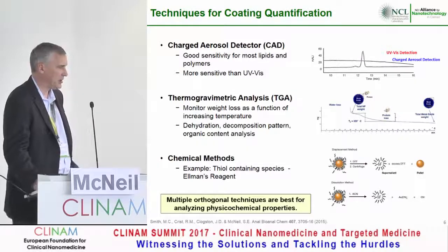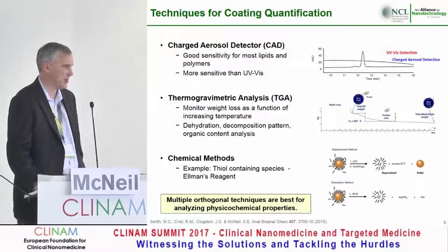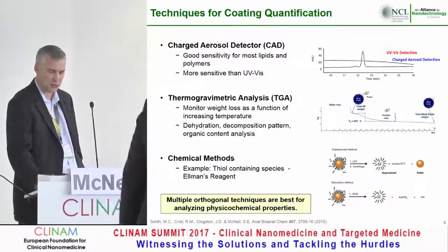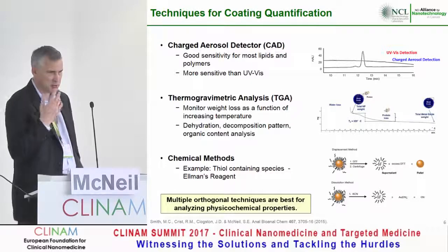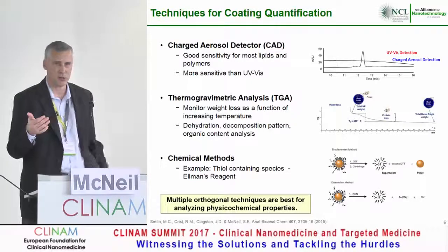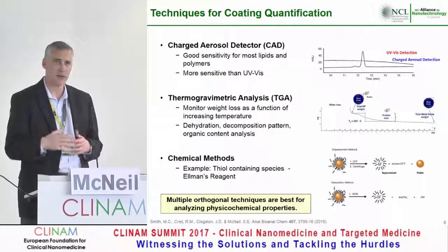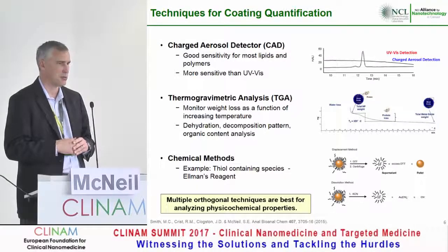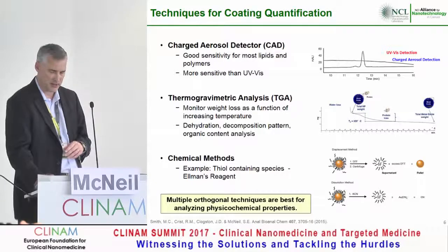And then various classical chemical methods, Ellman's reagent and doing thiol reduction, and as I showed you earlier, stripping off the pegylation layer in that one specific case. So also attempt to use orthogonal technologies where you're not chasing artifacts, so that you know that the measurand you're monitoring is confirmed by another technique.